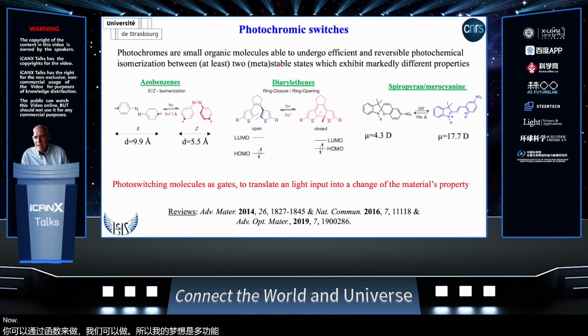Now, when I started my independent lab in 2003, we started immediately to play with photochromic switches, which are small molecules that can undergo isomerization from one state to the other as a response to a light stimulus. It can be, for example, irradiation with UV light. Everyone knows the case of azobenzene, which can switch from the E to the Z with UV light and go back thermally or with visible light. Directly, one can switch between the two thermodynamically stable states with UV light from open to closed, and from closed to open go back with visible light. Or spiropyran can go from the spiro to the merocyanine form with UV and go back with visible light or thermally.